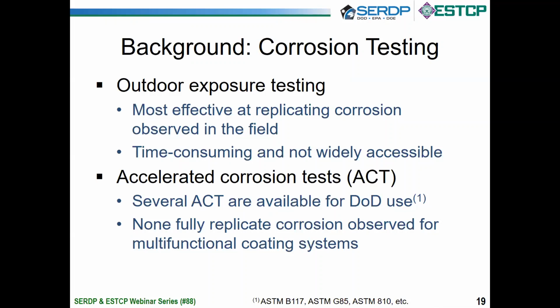But here's the problem. They don't fully replicate corrosion observed. And that's particularly true for multifunctional coatings, which are most of the DoD stuff, at least for external mold line. So coatings that act as barriers, but also have the ability to deliver inhibitors or metal-rich coatings to do protection. So as you start having more functionality coatings, these tests become particularly poor at defining performance. And you particularly see that when you're looking at rank order of systems.